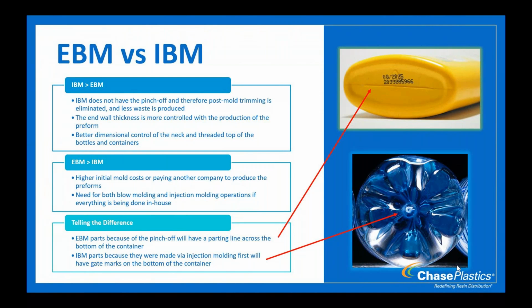You also have a little bit better control of your wall thickness because you injection mold your little preform, and that controls exactly how thick it's going to be with how much material you put in there. Versus extrusion, if a little bit more or a little bit less comes out, there's potentially more variation in your wall thickness. So it's better controlled with injection blow molding, and you get a little bit better dimensional control of the neck area and the threaded top. When you do bottles, containers, water bottles, Coke bottles, soda bottles, you have better control of the lip and the threads as well when you do injection blow molding.